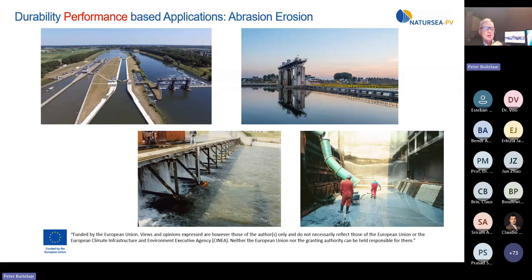Ultra-thin bonded UHPC toppings have been used since 1985 to repair concrete structures like locks and sluices in the Netherlands. The UHPC has been applied underwater by divers, and by floor layers where a temporary closure was possible. An annual 7 to 10 centimeter abrasion erosion by sand, larger materials, bicycles and other large objects has been stopped. Underwater inspection after 10 years showed a removed cement skin on top of the very hard aggregates.